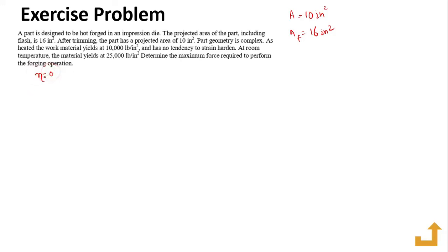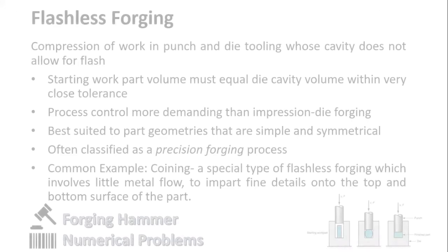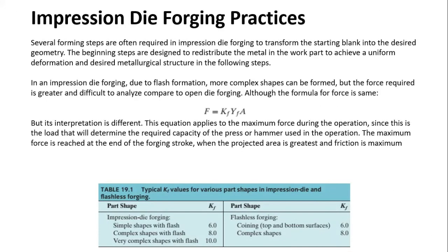Strain hardening would be equal to 0, and the value of the shape factor, as we have seen in the last part of this lecture, if you go through the impression die forging for the complex shape with the flash, the shape factor is equal to 8.